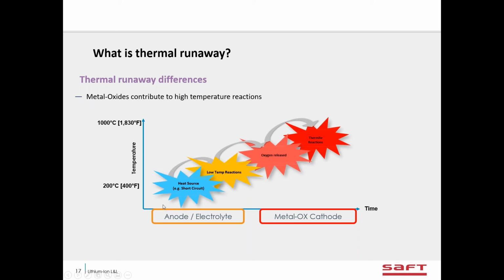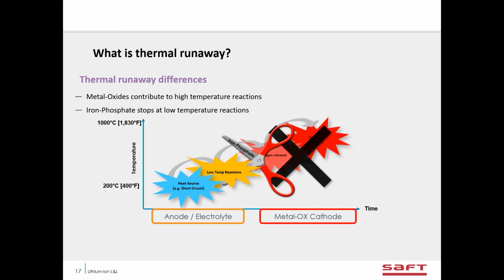And that can lead to the metals decomposing and what we call thermite reactions. And now you're talking of temperatures approaching 1,000 degrees C. These are very high temperature reactions. And that often can lead to propagation within a module or within a cabinet, where one cell goes into thermal runaway. It gets so hot that it starts the one next to it, and then it becomes a domino effect through the battery. But with iron phosphate, the oxygen is bonded chemically much stronger on the cathode, so that oxygen is not released into the thermal runaway condition. So iron phosphate cuts the high temperature reactions from happening, and we don't get the oxygen release in the thermal runaway at the very high temperature. So this is a big difference between iron phosphate and the metal oxide versions.